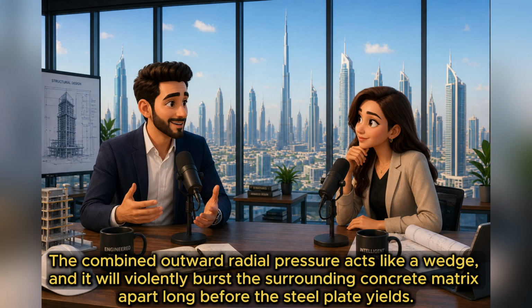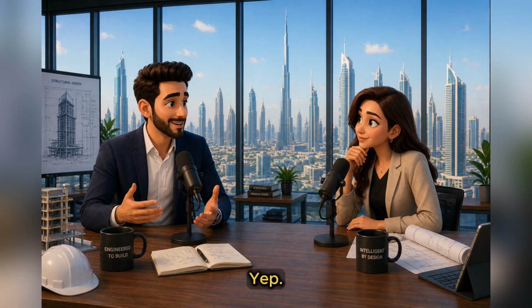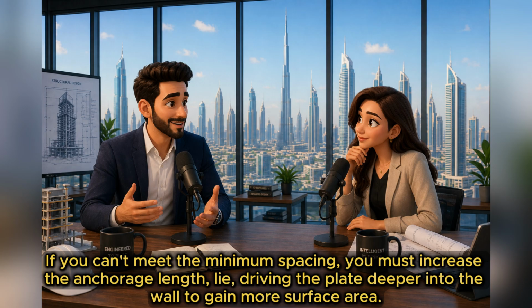If you place the studs too close together, those highly stressed compression cones overlap. The combined outward radial pressure acts like a wedge, and it will violently burst the surrounding concrete matrix apart long before the steel plate yields. You lose all anchorage instantly. Yep. If you can't meet the minimum spacing, you must increase the anchorage length, i.e., driving the plate deeper into the wall to gain more surface area.